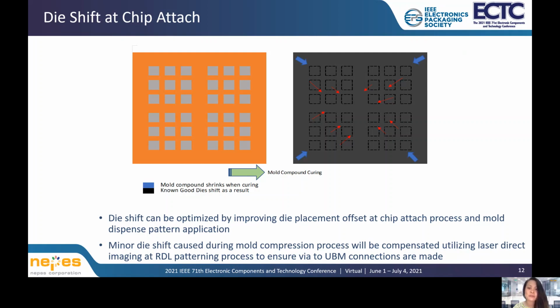Die shift can be optimized by improving die placement at chip attach process and mold dispense pattern application. Now, we need to note that even if the TTV is well within specification, there will likely be slight die shift and would impact the RDL patterning process. To compensate the minor die shift caused during mold compression process, a laser direct imaging process during photolithography is applied at RDL patterning to ensure via to UBM connections are made.